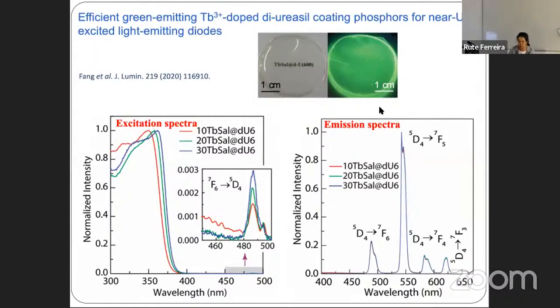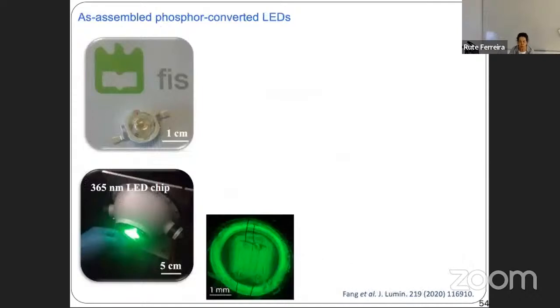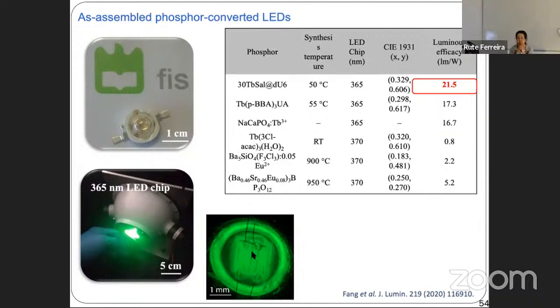So this material was used to coat a commercial ultraviolet chip, in fact one emitting at 365 nanometers. These are real photos of our prototype. You can clearly see that the film was deposited over the interior where the electroluminescent LED appears. And finally, just to give you some figure of merit to have an idea about the performance of this prototype, here we have a luminous efficacy up to 21.5 lumens per watt.